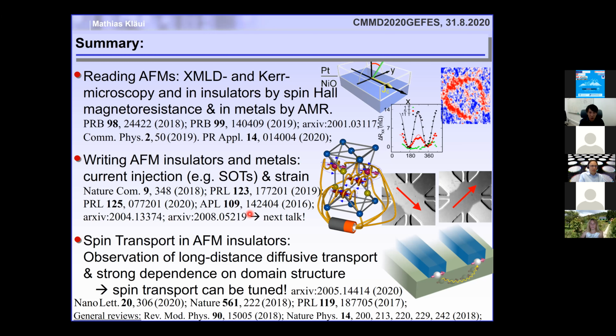So manganese, you showed some manganese-based anti-ferromagnet. What about the ones that are traditionally used in exchange bias systems, for example, platinum manganese, iridium manganese? Yes, actually, there is some confidential information that they can also be switched. So I think there was a talk given by someone. So they also work. There are a couple of problems with these. One problem is that very often for the exchange bias, you're not using necessarily the collinear phase, but you're using these non-collinear phases. And the problem with non-collinear is, how the heck do you read it out by imaging?